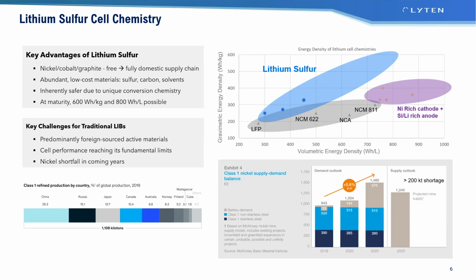One of the other reasons is because as the lithium reacts with the sulfur, the sulfur itself dissolves into the electrolyte, and you get what you call polysulfides, and those polysulfides want to move to the anode, and want to passivate the anode. And this is something they call a polysulfide shuttle, which is a practical limitation of lithium sulfur cells. So you have to address that.